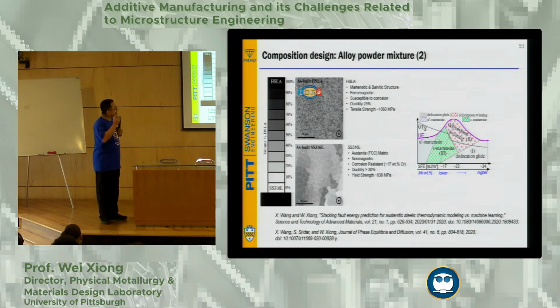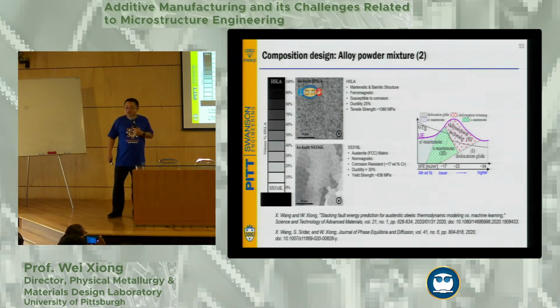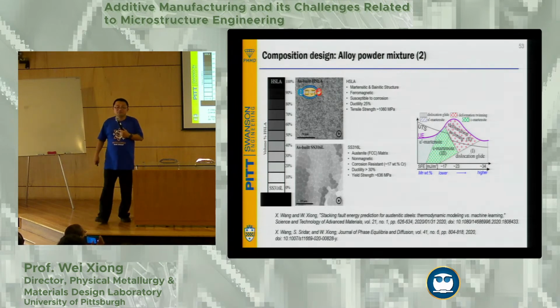So if you think about the stacking fault energy level - because this part is easy for martensite, this part is difficult for martensite, and if we mix them together, in the middle you will possibly have a regime where you introduce TRIP and TWIP effects. That's fascinating, right? No one studied this before.